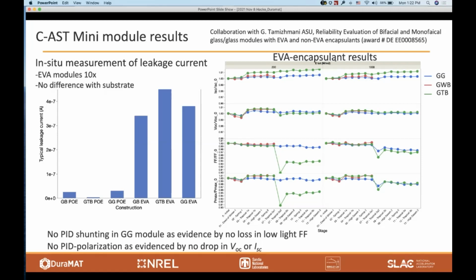And VOC here, other than the situation where you have the break, is fairly consistent, doesn't move beyond 0.5%. So I think we have to consider here that combined accelerated stress testing uses the factor of light, which will influence whether you see a PID or not. Because light has a neutralizing effect on PID. So it highlights the importance of using the stress factors of the natural environment to see if you've got a problem or not.